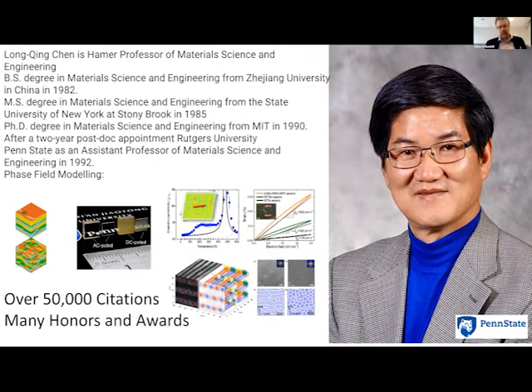from precipitation, coarsening, grain growth, crystal growth. He's looked at dendritic growth. He's looked at more recently in the ways of even applying electric field and an AC electric field to then being able to make PMN-PT crystals transparent. And this has profound implications in terms of potential acousto-optic medical devices. He's also worked with Venkat and Ramesh at Berkeley on these skyrmions, these metastable forms that can be quenched in, that then create these vortices of polarization stabilized by localized charge.